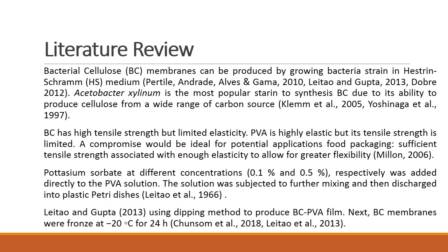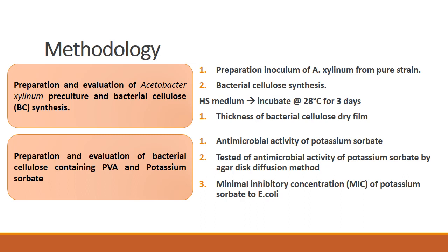For the antimicrobial agent, potassium sorbate is chosen as it is most commonly used in the market. Potassium sorbate will be mixed with PVA solution and later dip coated using the bacterial cellulose synthesized before, and after that the new composite film will be freeze dried for cross-linking to happen.